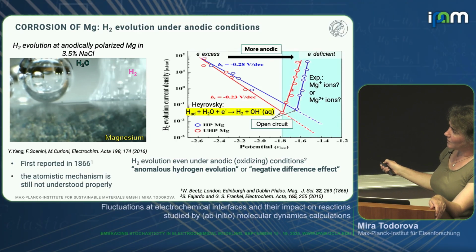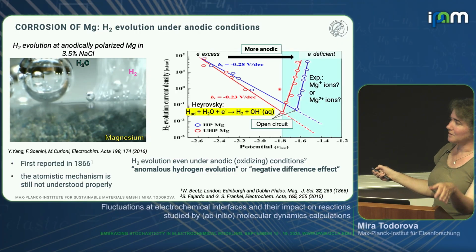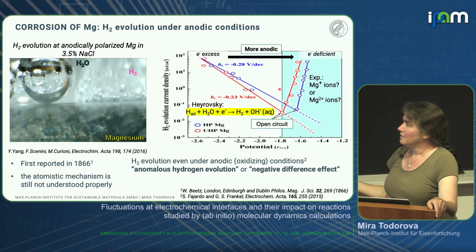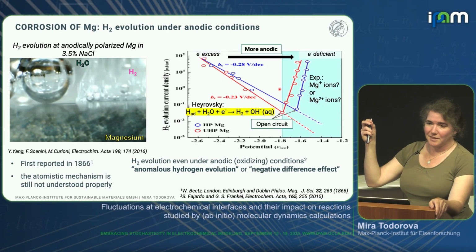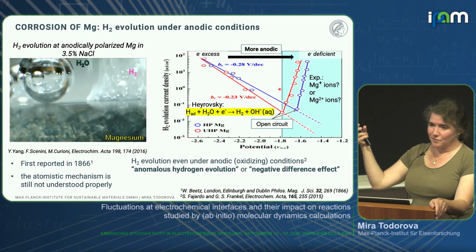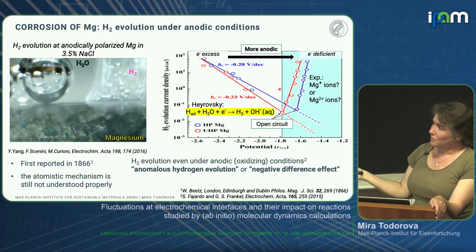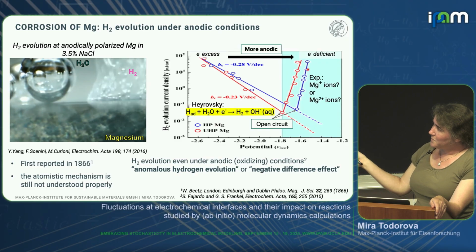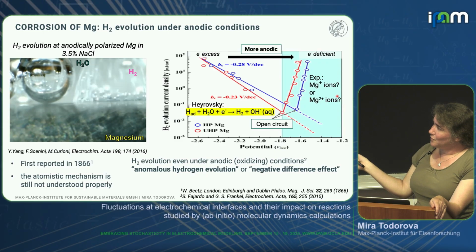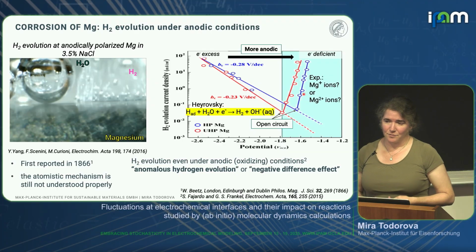That's not the case. One can see experimentally that the curves show an increase in hydrogen evolution. Also, if one looks at the amount of magnesium that is dissolved during this reaction, which is enhanced, and the amount of electrons, or the hydrogen that is found, one must use a magnesium 1+ ion in order to explain the ratio.